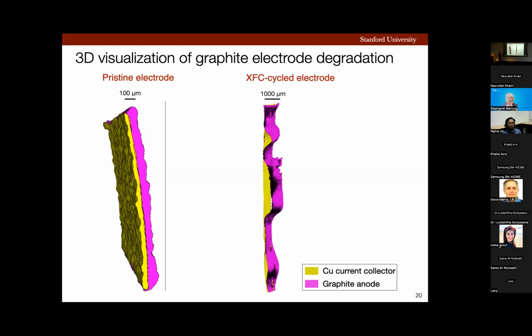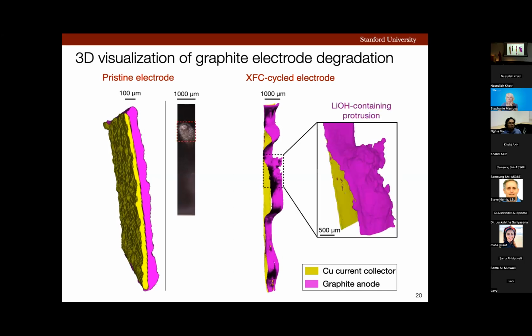However, if you look at a 3D visualization of the XFC cycled electrode, we can see some of the delamination, and we can see this giant lithium-containing protrusion very clearly, which can be directly correlated to this brightish deposit on the optical image of the graphite strip. Now, this is 3D data. We can correlate this 3D visualization to certain regions along the length of this graphite strip.